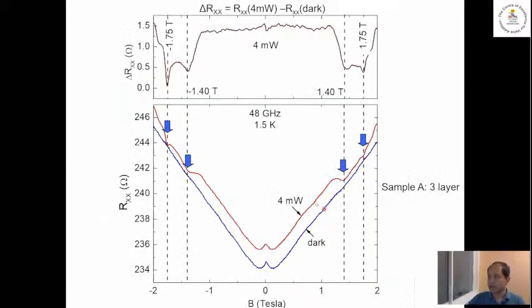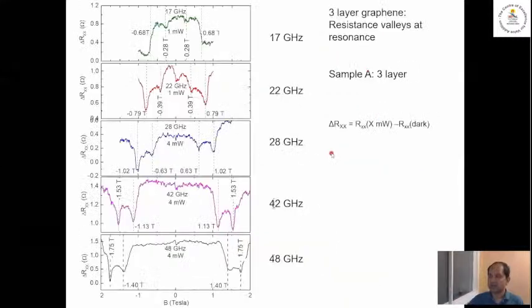So what we can do now is subtract the blue curve from the red curve. Subtract blue from red, and then we get black. Notice this black curve highlights our resonances. There's one at minus 1.4 and 1.75 Tesla, same at plus 1.4, 1.75 Tesla. This is the 3-layer sample. So that was at 48 gigahertz.